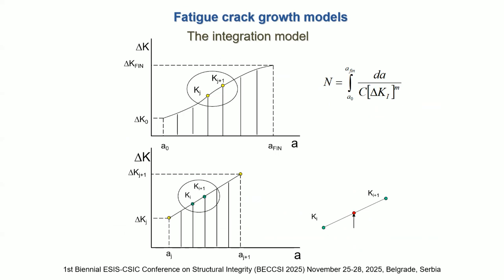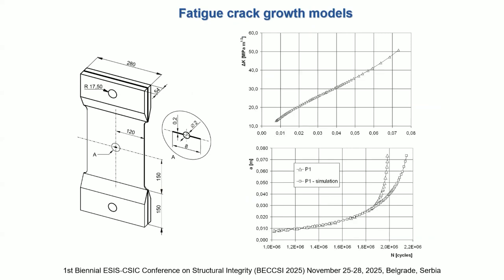And basically what we have here is a straight line between two points for which we calculate K. So a piecewise linear curve for which we calculate the stress intensity factor by finite element method, and we will integrate this equation directly. So stress intensity factors calculated for P1 specimen are shown here, and that's very easy to do for one specimen with a single crack.